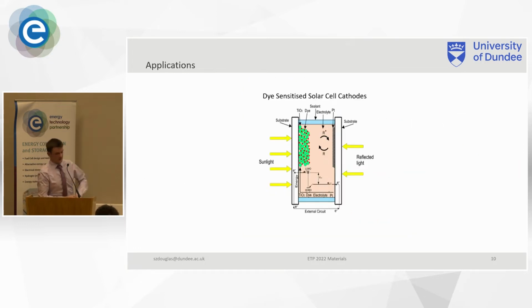So the application I'm applying this to is dye-sensitized solar cells. If I just talk about what a dye-sensitized solar cell is, for those who don't know, a dye solar cell is a solar cell that has a mesoporous semiconductor layer, which is coated in a dye sensitizer. The dye sensitizer absorbs light, which then transfers the electrons to the semiconductor, which is then diffused into the external circuit, then returns through the cathode, which is what I'm printing with the platinum, and then the platinum acts as a catalyst to the reaction to transfer the electrons back to the electrolyte, which then reduces the oxidized dye molecules back to their original state, so we can restart the system.